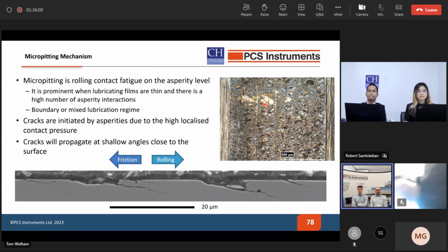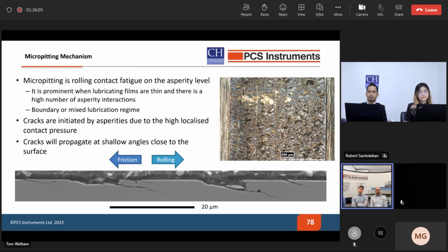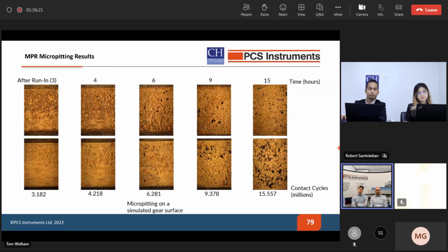And you can see here a surface generated on an MPR specimen, and there are many cracks and pits being formed, and it's continuous. You'll basically regenerate the surface over and over again, and if you can maintain the same conditions as the MPR can do, you can generate a lot of damage very quickly. So here we have a few more examples of MPR testing.